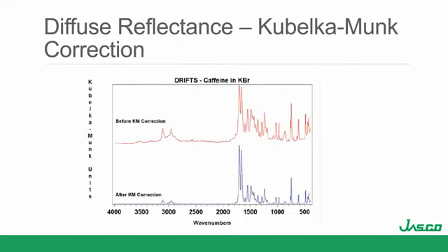And then that pad's rough enough to where you can do really good DRIFT on it. This has a small issue where, as the wavelength changes, the spectrum changes with wavelength. So relative to the transmission, it looks different. So what you do is you go through a Kubelka-Munk transformation, which changes not the position, but just the relative intensities of these. And that comes out as KM units.